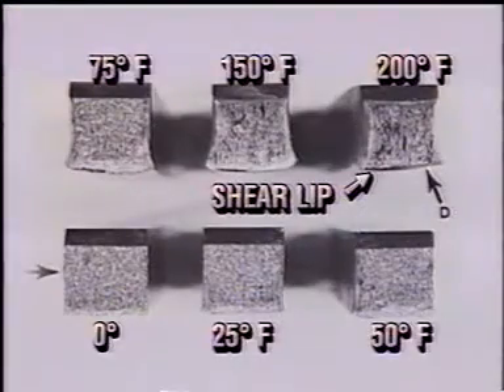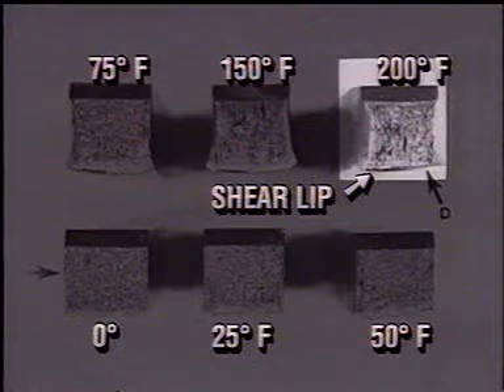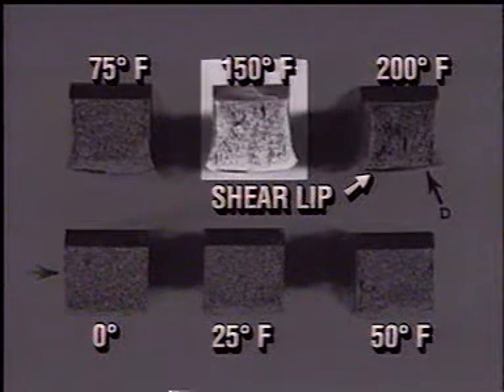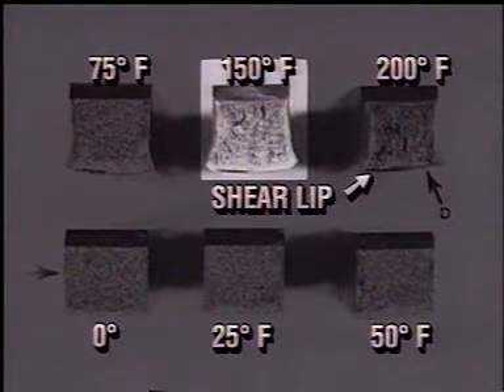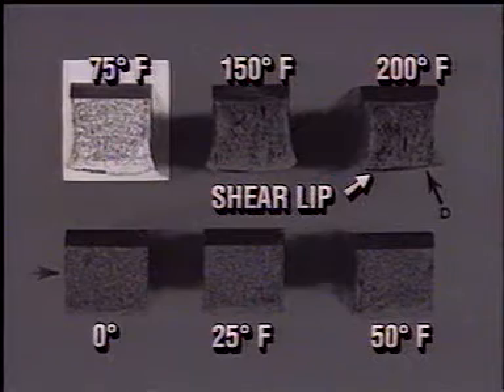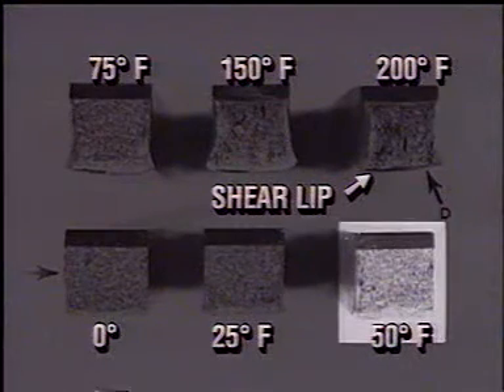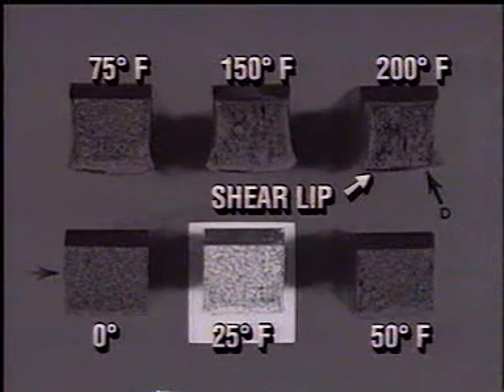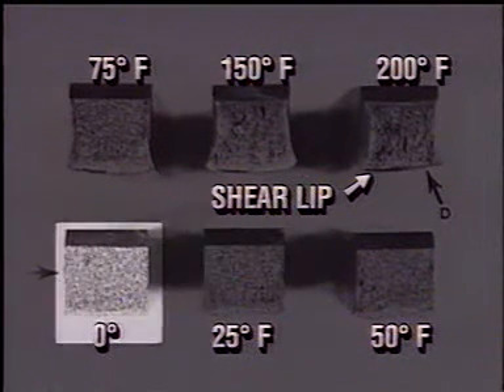The results of tests conducted on a low-carbon steel show the drop in absorbed energy as the temperature decreases. The transition from ductile to brittle fracture is made visible by a decrease in the amount of lateral expansion on the compression side of the specimen. The shear lip is reduced as the test temperature decreases, and the appearance of the fracture surface changes from a rough ductile fracture to a relatively smooth, flat, brittle fracture.